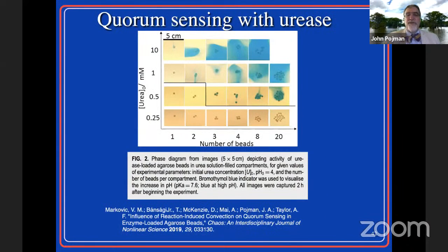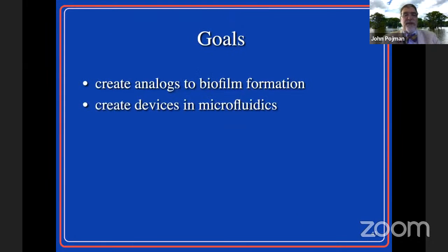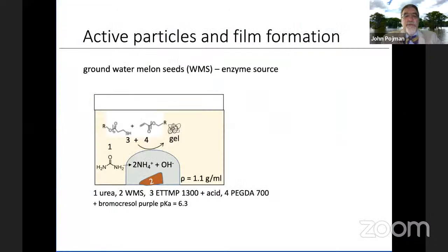And with Dr. Taylor, we studied what's called quorum sensing, which means you need a critical number of particles before you have the clock reaction. This was showing that if you have, say, just one particle at this concentration, it will never undergo this abrupt increase in pH. But under a certain situation, if you go from 2 to 3, you can get the behavior. So they act together in a cooperative behavior, which is similar to how bacteria form biofilms. We're right now trying to create analogs to biofilms and devices in microfluidics.